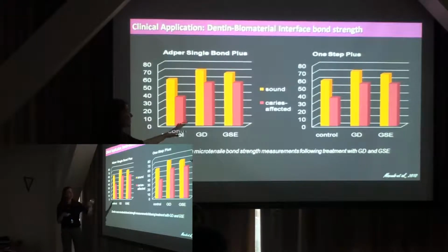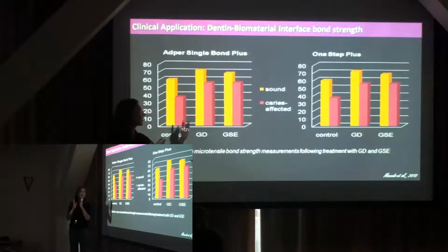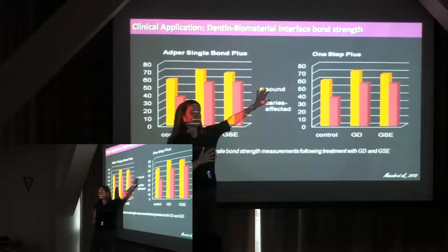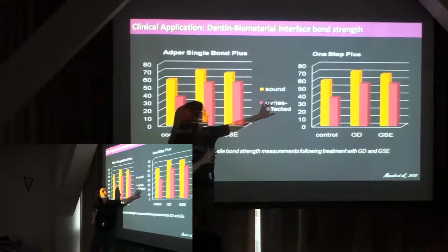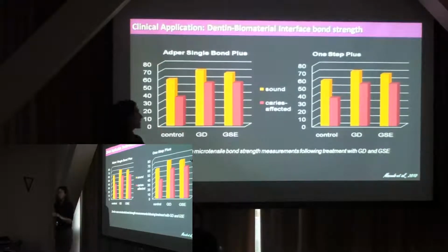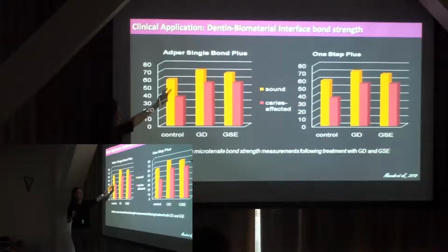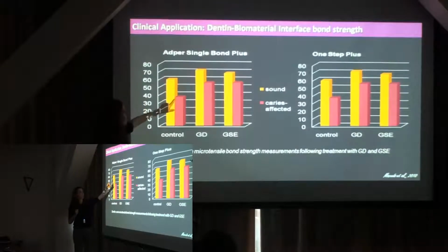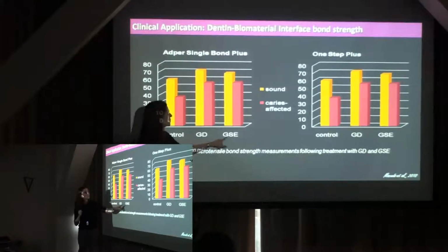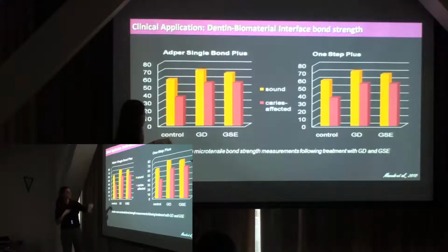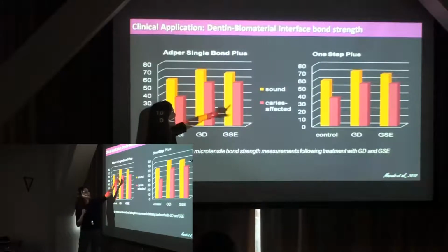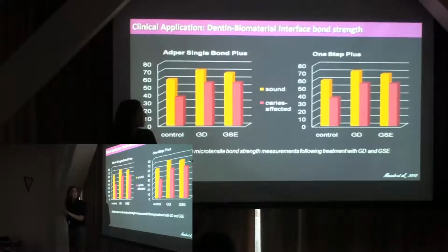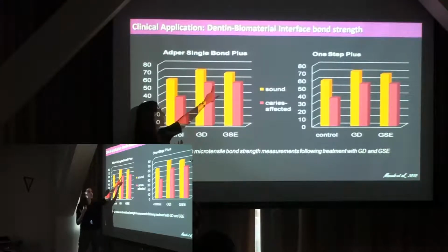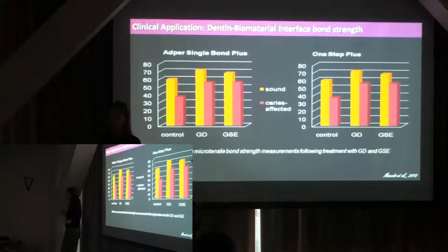With this test, we have the ability to decide where we want to cut it. So we cut in the dentin that's very sound, never had decay, and the dentin that had a decay process. So when we look at it, you already see a difference between sound and decayed. The bond strength of the decayed dentin is already significantly lower than the sound, right? So when we introduced glutaraldehyde or grapeseed extract, we saw an increase in the bond strength for both, and it was also more pronounced on the caries-affected dentin.